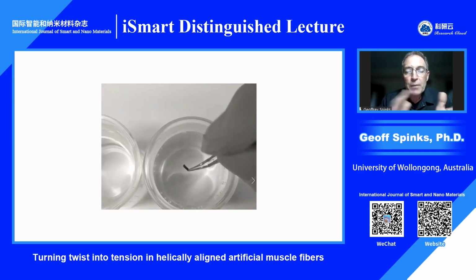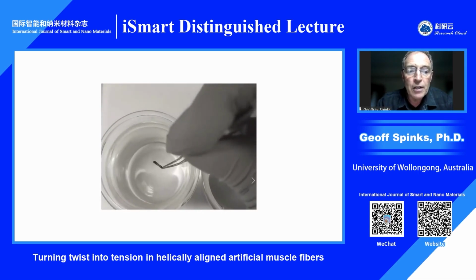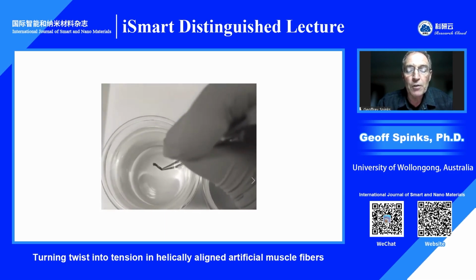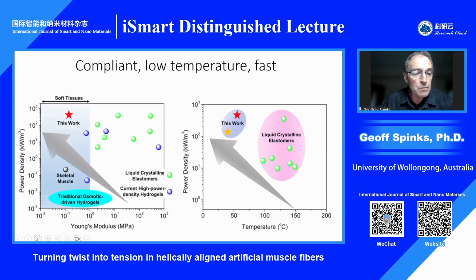So the water temperature is only a few tens of degrees, and you can see a really large and rapid response in these liquid crystal elastomer twisted and coiled fibers. In terms of performance, these charts highlight the main advantages. On the right, what we're emphasizing is firstly power density on the y-axis, and temperature. These liquid crystal elastomers are operating at just 40 or 50 degrees transition temperature, much lower than most other liquid crystal elastomer systems, which can be 100 degrees or more. So there's a big advantage in using this chemistry.